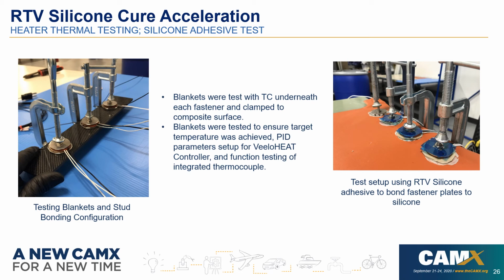We did see some variation between the integrated thermocouple and the surface temp, so we made note of that during our subsequent testing. Here on the right, you can see the test setup, now using the RTV silicone adhesive, and also the blanket that we were bonding the studs to. So here you'll see, again, the clamps.